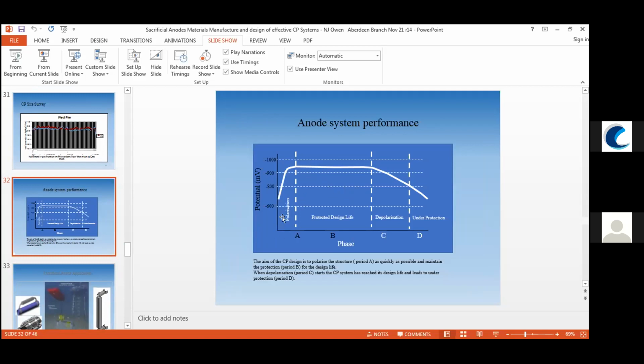We've talked about putting anodes in, so this is just showing you what happens when you actually put an anode on a wall or on a system. You basically go through this. The potential of the steelwork is actually rising as it gets drawn towards the anode. And this is when you get polarization of the steel. And then the protected design life is where you've got a constant sort of current going on. It's slightly dropping off. And then you start to get end of life depolarization.